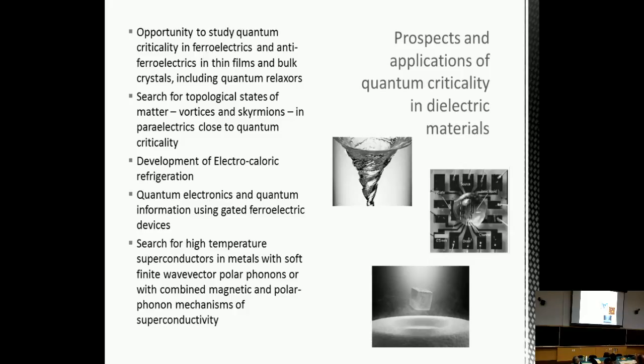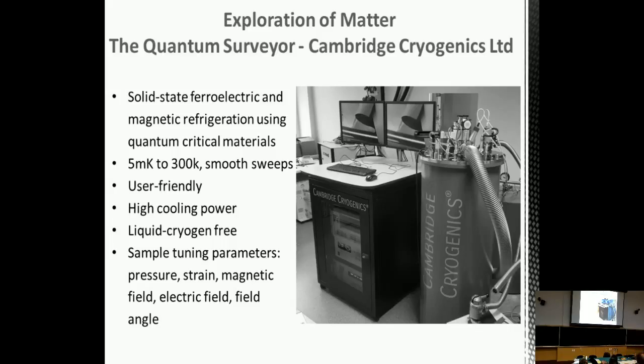For applications, these materials also have a strong electrocaloric effect, where you can apply electric fields at low temperature and get large refrigeration capability. And then there's an opportunity to search for more superconductors of this kind. On the electrocaloric front, we're now developing ferroelectric and magnetic refrigerators using quantum critical materials, which have a large magnetocaloric or electrocaloric effect. These systems can go from around 5 millikelvin to room temperature with smooth cycles, completely free of liquid helium, no helium-4, no helium-3. And it's very easy to have many tuning parameters here: pressure, strain, field angle, and so on.